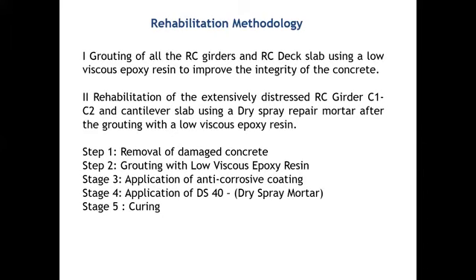Remove the damaged concrete, grout with low viscous epoxy resin, and then apply an anti-corrosive coating and DS40 dry spray mortar, because for the bridges you will not be able to go with the regular micro concrete jacketing, and then curing is done.